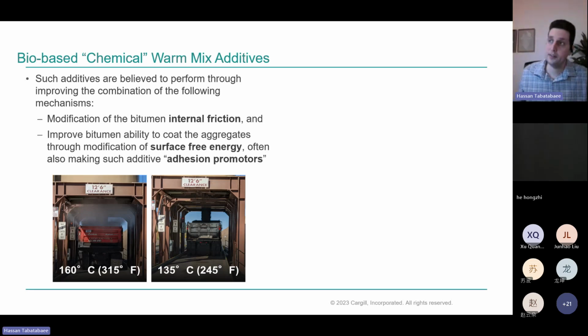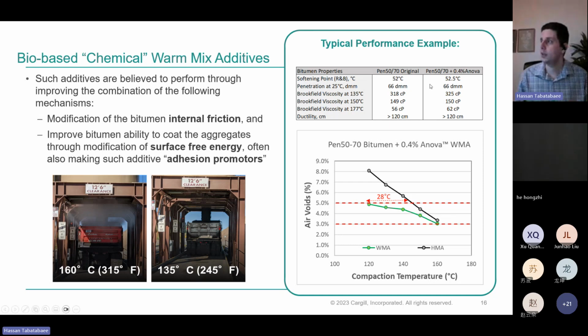As I said, what makes these more attractive than a wax is the fact that they do not change the grade of the bitumen. As you can see, you can achieve significant drops in production temperature, and sometimes much lower than the temperatures even seen in this example with the use of such additives. An example here is showing how the use of a bio-based warm mix additive is not changing the rheological properties of the bitumen. You can see softening point, penetration, even viscosity is not changing much. It might even in some cases look slightly higher, but statistically not changing.